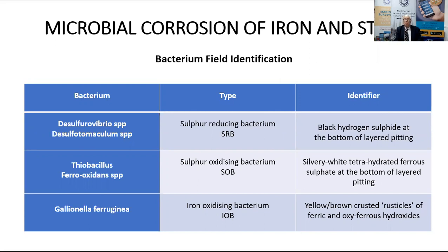The question is, once you've discovered it, once you've identified it, what do you do about it? The discovery by a marine surveyor of such microbiological corrosion is often very difficult and requires some experience because it's not always readily visible. It is usually found under muddy and slimy surfaces, sometimes even behind paint coatings, and a very careful visual inspection is necessary to locate it, and the marine surveyor to know exactly what he is looking for. It's not amenable to discovery by non-destructive testing, such as ultrasonic thickness testing measurements, eddy current testing, or the magnetic methods familiar to most marine surveyors.